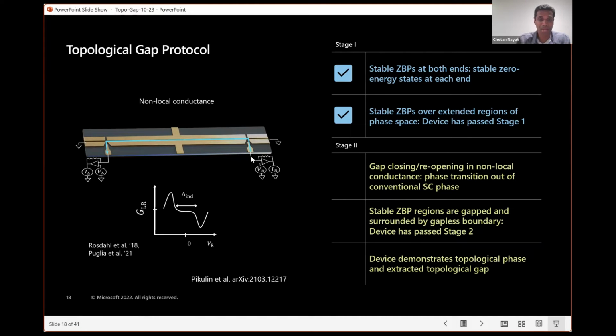So we look at the non-local conductance. That's dominated by, it looks like this. At low bias voltage, it's basically zero because you can't push any current in. The system is gapped. The semiconductor is gapped because it's inherited superconductivity. The superconductor is gapped. If we go to very high bias above the gap of aluminum, then you can just push the electrons straight into the aluminum. The aluminum is grounded, they just run to ground. And so they never come over here.